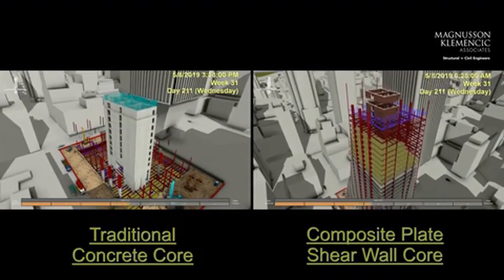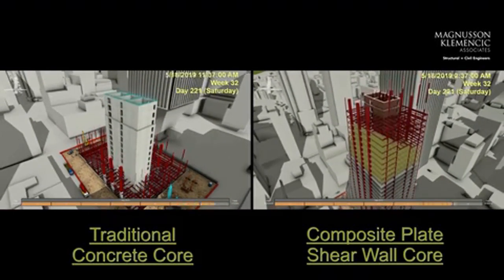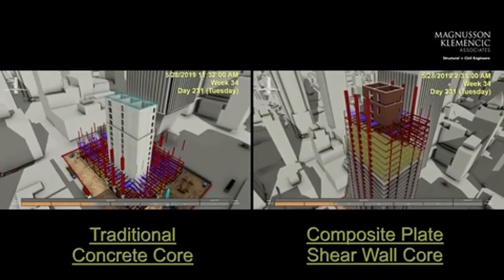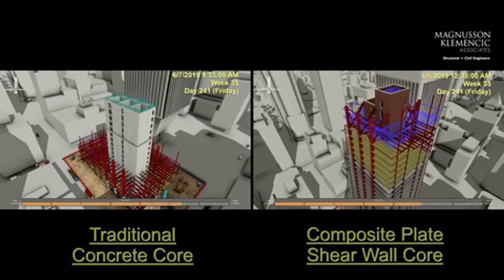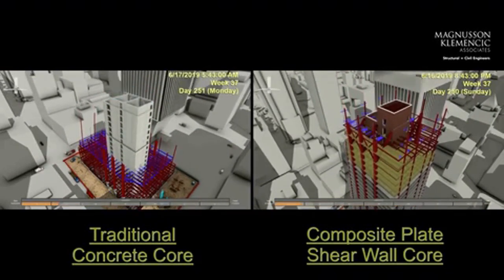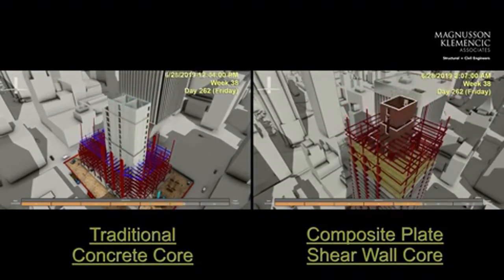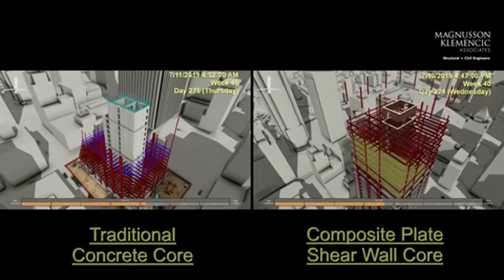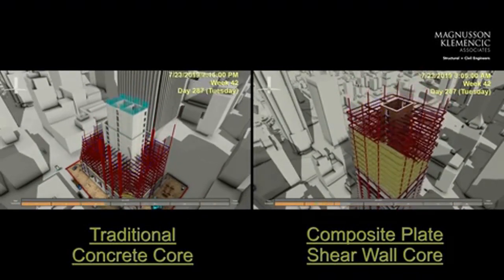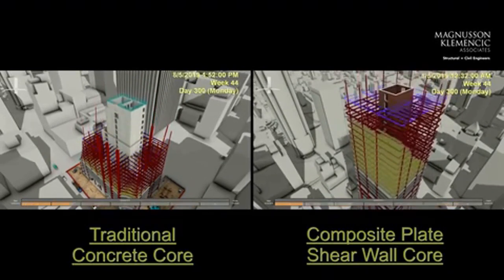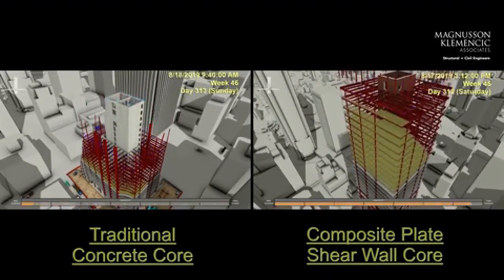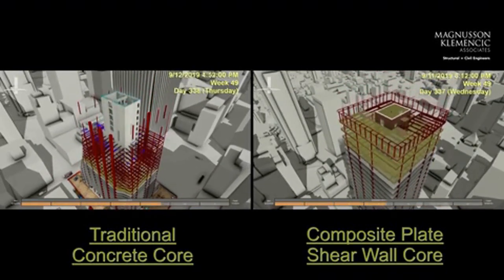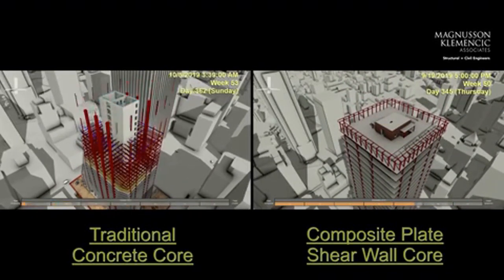This video has now been updated, and what you're seeing on the right is the actual day-by-day sequence of what really occurred in the field. The building is now topped out as of about a month ago, and what you see on the right is what was actually achieved day by day. And what you see is that we are already at the Outrigger level on the version on the right, and we are barely getting out of the ground on the left. The core is jumping up, and we're nearly just about 1/3 of the way up when we're already 2/3 of the way to the top on the picture on the right. So as we're approaching August 15th of this year, which is about 6 weeks ago, we had our topping out. That is the date which you'd see over here on the right of the screen.